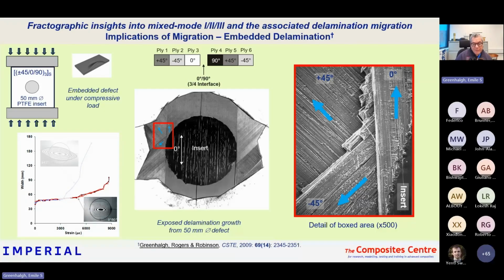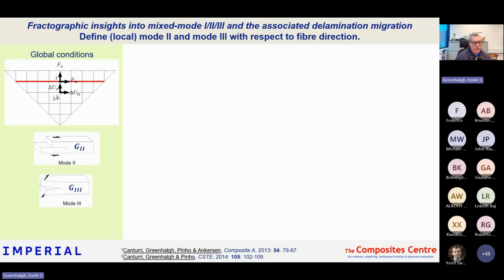And this is all related to that migration process. So we tried to scrutinize what's actually going on here. So we started to rethink the definitions of mode 1 and mode 2 and mode 3. So from using a virtual crack closure type methodology, you can define a mode 2 in this type of instance, and then a mode 3, the tearing mode, as transverse to that.